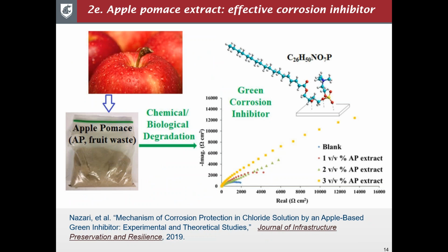So yet another feedstock we played with was the pomace of apple, or the waste of apple after the industry has taken the useful or edible parts. So again, this process produced a very effective corrosion inhibitor. Actually, after 2 weeks of testing in the lab, the corrosion inhibition reached around 90%, actually 98%. So we also studied the science behind it, and it looks like what's working is really this organic phosphate. It tends to serve multiple functions. For instance, it makes the metal surface more hydrophobic, and also makes the rust denser, and therefore protects against further corrosion attack.